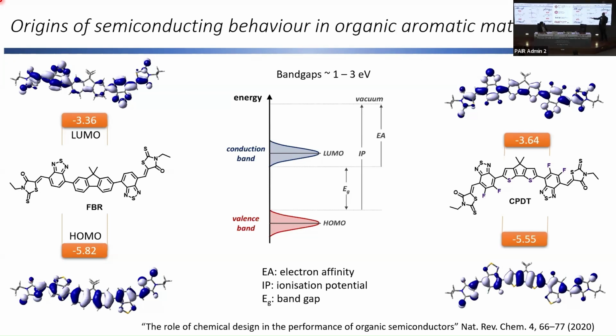But most semiconductors now have energy levels about 5.3, 5.4 electron volts. If it's very deep, then the actual polaron, so in operation, is very unstable. There are also traps all the way through of different energies in your semiconductor. So if you remove an electron from the HOMO, you've got your hole. The hole can fill all the traps above it. So the deeper the HOMO energy level, the more the trapping that can happen above it. So you want to try to push the energy level up this way to avoid all these traps. But when you do so, it's now susceptible to reduction. So again, that's a trade-off.